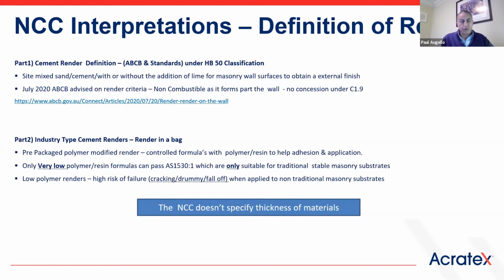What happens when you put these low polymer renders onto a substrate that's not traditional? What will happen over time is they can go drummy and basically crack and allow them to fall off the wall. And we've seen that over the decades. That happens continually all the time as well. The other point to note is that the NCC, in the 2019 version, has never defined what a thickness of a render material can be or can't be, nor a non-combustible render in that respect can be or can't be as well.